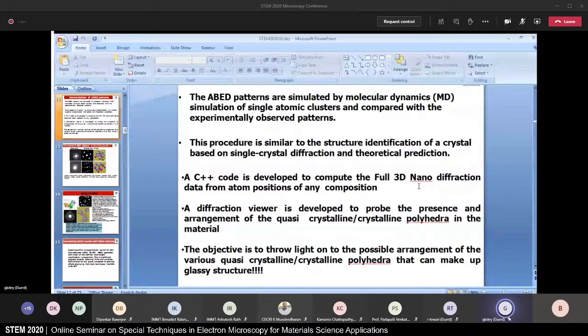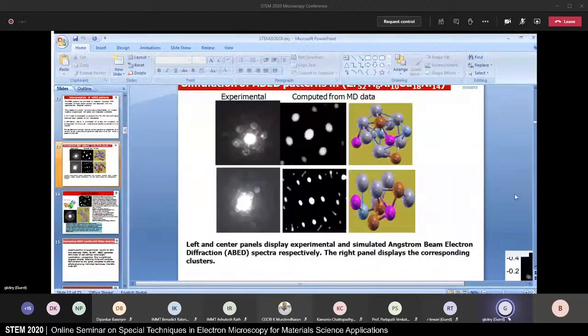Now we have our own result. This is in a multi-component glass where I show the observed angstrom beam diffraction pattern, and this is the simulated structure, and then we have the observed and simulated diffraction patterns. There is very good agreement between the two.